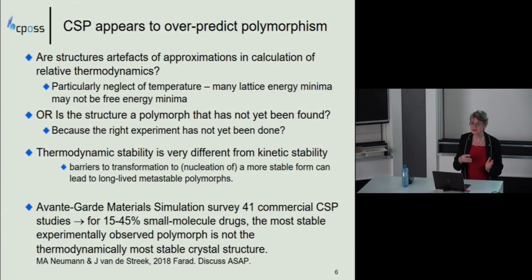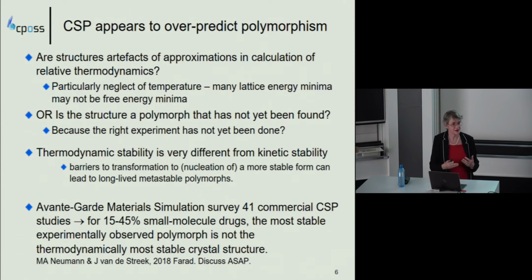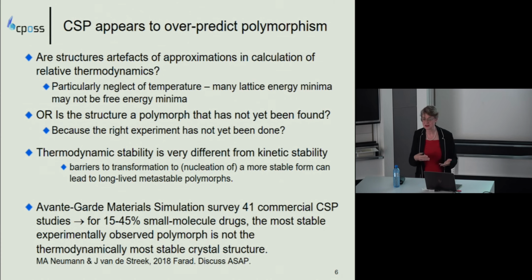recent Faraday discussion on crystal structure prediction, which was just this summer and was a very useful discussion on this, presented a paper where they surveyed 41 of their commercial CSP studies, and with an estimate of the errors in their calculation, made this estimate that for a large proportion of small molecule drugs that are currently on the market, the experimentally observed most stable polymorph is not the one that they are finding as the most stable structure. So risking the disaster of the ritonavir case, or there have been other cases. Ritonavir was a case where they had to completely reformulate when people on the HIV treatments could no longer get the drug that was licensed, because they could no longer manufacture it. So that's one way of looking at these minima.